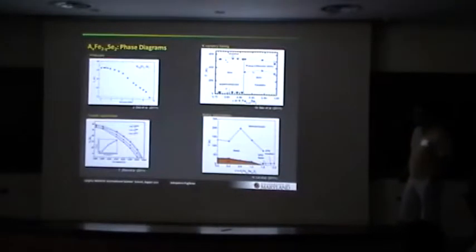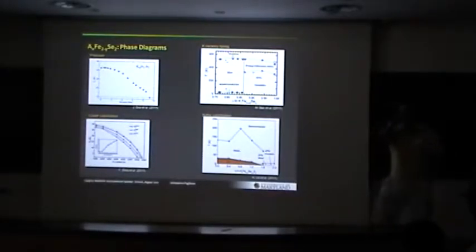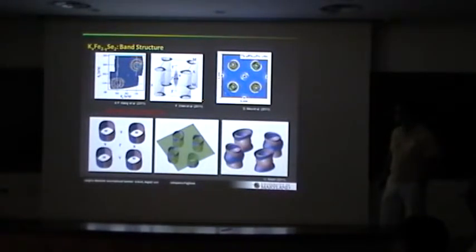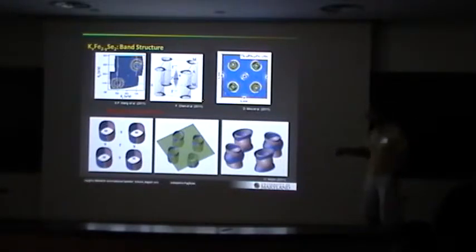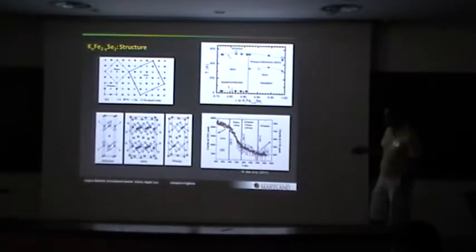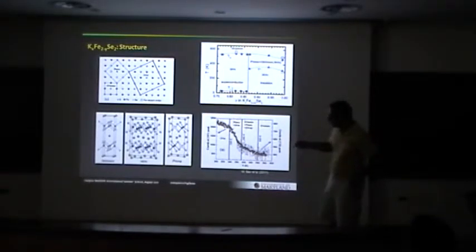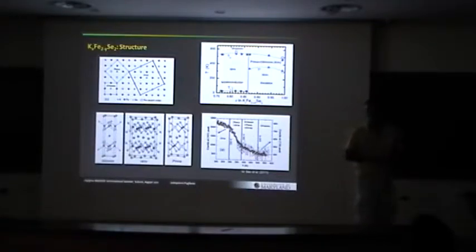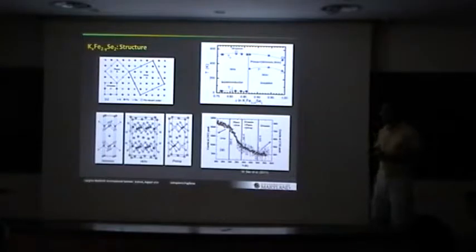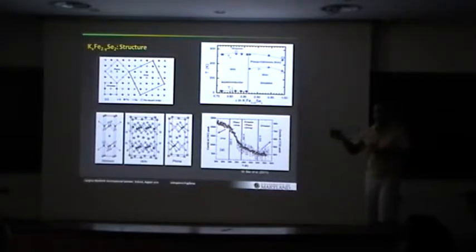Okay, yeah. I do have a question on that ARPES data. So far, what's seen in literature is that those compounds are very hard to grow very clean. So there's quite big disorder also because it's probably not 1-2. How wouldn't that affect the ARPES, since this is very surface sensitive, and might that be misleading to the band structure and what they actually see? I'll get to that. Yes, but it is 1-2, or at least it has a 1-2 symmetry. Yeah, but it's probably not stoichiometric, from what we see from X-ray. Yeah, so there's vacancies, potassium.